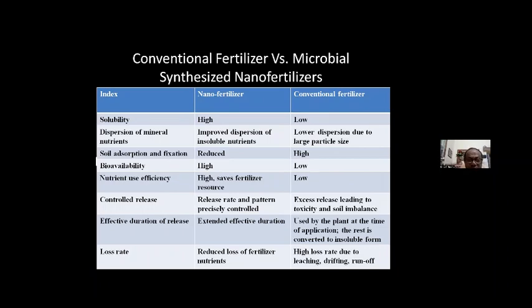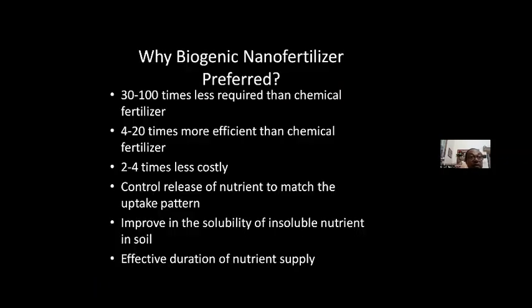Release rate and pattern is precisely controlled. Effective duration of release is extended. In the case of nanofertilizer, we found the duration of release even goes up to 50 days, but in the case of conventional fertilizer, only 4 to 10 days. And it reduces loss of fertilizer nutrients. Then why should biogenic nanofertilizer be preferred? Because 30 to 100 times less is required than chemical fertilizer, it is 4 to 20 times more efficient than chemical fertilizer, 2 to 4 times less costly, with controlled release of nutrients to match the uptake pattern, improved solubility of insoluble nutrients in soil, and extended effective duration of nutrient supply.